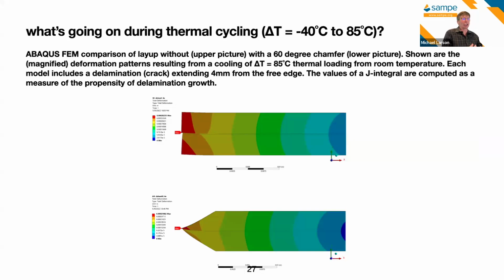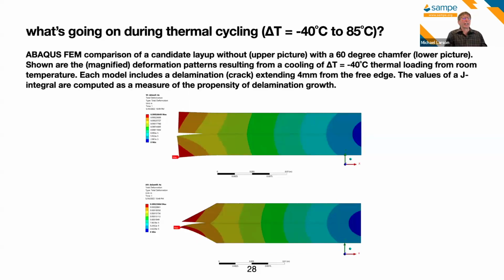And here are some figures out of Abaqus showing a magnified deformation for the hot side of that temperature change. And so in this case, what we have is the top part is expanding and making life difficult for that leading edge of the delamination. And in the bottom, with the chamfered edge, it is less likely to grow that delamination. This is for the carved in 4 millimeter delamination from the edge, looking at particular values of the energy available for driving the crack. Again, much less.